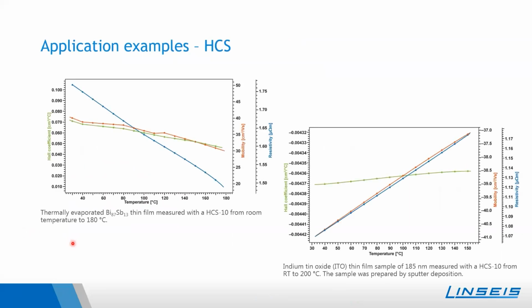Here is also an example performed with the Hall characterization system. A bismuth antimony thin film was measured. The Hall coefficient and the mobility were tested, as well as the resistivity, in dependence on temperature. There's also an example of indium tin oxide with a thickness of 185 nanometers. This was measured with a Hall system from room temperature to 200 degrees Celsius. Here one can see the Hall coefficient does not change that much with temperature. However, the mobility and resistivity show a stronger dependence on temperature.